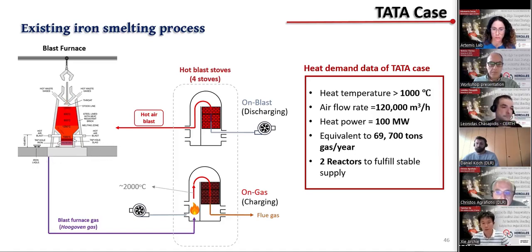The first scenario is based on Tata Steel's iron smelting process. So how does the existing process work? From the diagram, you can see that there are 4 stoves to serve the hot air to the furnace. There are 2 working statuses of the stove: on blast and on gas. You can think of them as the discharging and the charging process of the storage system. In the charging status of the stove, the combustion of furnace gas will heat the bricks in the stove, and actually the bricks work as a kind of sensible heat storage.